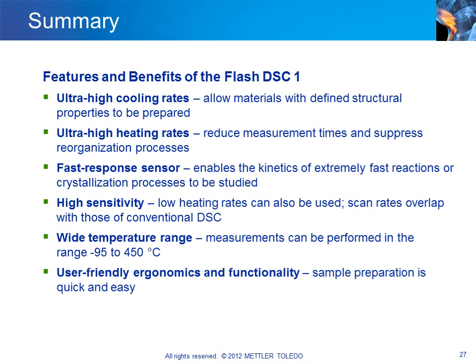The ultra-high heating rates reduce measurement times and can be used to investigate reorganization processes or to prevent reorganization from occurring. Measurements can also be performed at relatively low heating rates thanks to the high sensitivity of the Flash DSC-1. Due to this, the heating and cooling rates overlap to a certain extent with those of conventional DSC. This allows for direct comparison of experimental results. The temperature range of the Flash DSC-1 with the multi-star UFS-1 sensor is -95 to +450 degrees Celsius. The application-oriented ergonomics and functionality enable easy and rapid sample preparation.